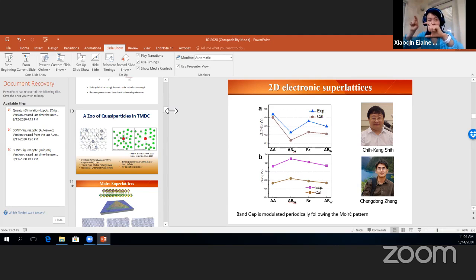Okay. So even in the monolayer, you can have both intravalley and intervalley trions, two species of trion, depending on whether the excess electrons sit in the same valley or the opposite valley. Okay. So we have a lot of pseudo spin to play with here. Layer is a pseudo spin, valley is another pseudo spin. So sorting them out is not always easy in spectroscopy. So you need a control sample where you control the doping level. And of course, fortunately, there's a little bit of energy difference between these two types of trions. Yeah, there's a lot. And then everything gets three times more difficult with the Moiré.